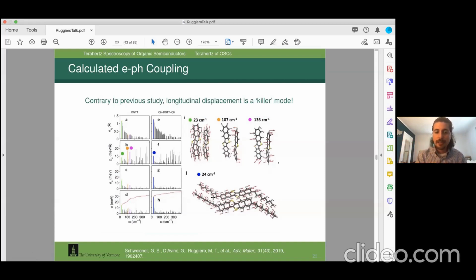By shifting them to higher energies, we reduce the amount of thermally activated motion, which reduces the value of the product, for example, of E and F, and reduces the overall effect, basically.